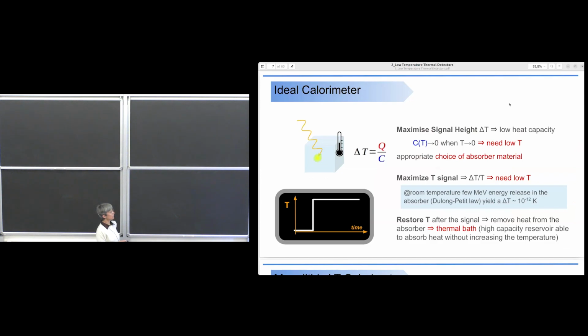So now we have a temperature increase, and our problem is to read out this temperature increase. The strategy to be sensitive to this temperature increase is to maximize the signal. It's what we do for whatever detector. We want to design our detector in order to have the best signal. And to maximize the signal, we have to reduce the heat capacity. So this is the first solution that we have to adopt when we want to build a thermal detector: choose an absorber that has a very low heat capacity.